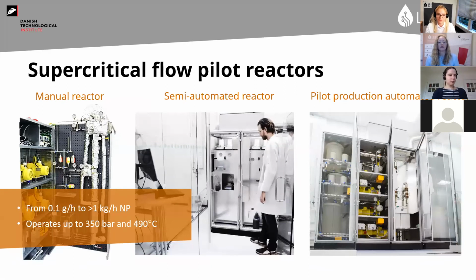Another method we have is the supercritical flow reactors. This is a different way of doing synthesis. We have 3 different ones. We have a manual reactor, where we do the first synthesis part, and it's easier to adjust the tubings and stuff in this. Then we have the semi-automated reactor, and we have the pilot production automated reactor that is more process-minded, production-minded. And they can vary from 0.1 gram per hour to 1 kilo of nanoparticles per hour. The difference here is that, of course, it's in a flow, but it also works in a much more crucial or harsh environment.